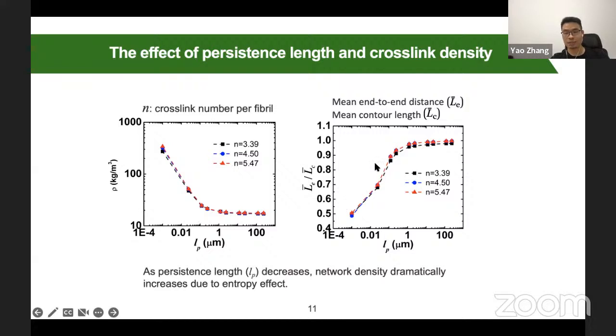And why? So we check the microstructure of the network in the equilibrium state. Here, LE bar is the mean end-to-end distance between two crosslinks, and LC bar is the mean contour length of the fiber between two crosslinks. If you look at the ratio of the two lengths, you can see that if you increase the fiber persistence length, this ratio just increases.